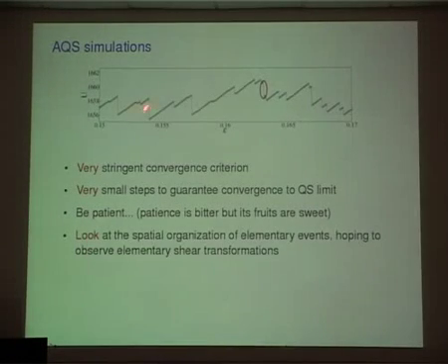Essentially these athermal simulations, because T is 0, and quasi-static, because the strain rate is 0, produce this type of curves. Of course, you need to be very cautious and use very small steps to resolve the elastic branches. And the question is now to understand what happens during these plastic events.